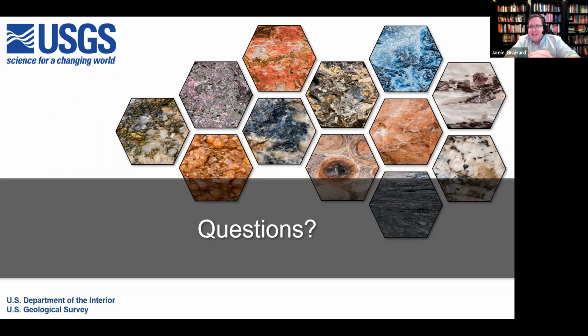And unfortunately, there's not a tailings pile, particularly if it was a precious metal mine, left in the United States that hasn't probably been reworked at least once in the past couple decades, because people are going to go back at least for the gold. Unfortunately or fortunately, gold, precious metals tend to drive everything. And so this becomes a real problem for some of these byproduct materials, like tellurium is one of these great examples of, okay, they electrowin, they go through anode slimes that are relics from doing copper processing to get tellurium, but they get gold first.